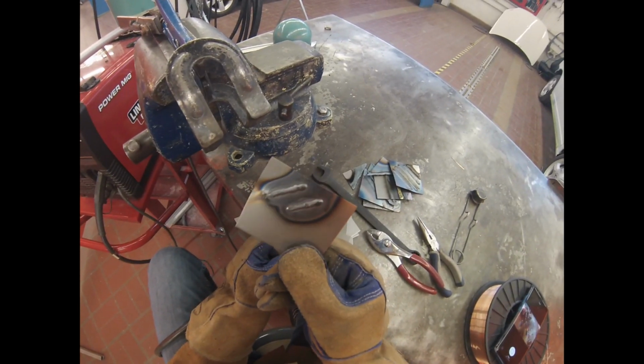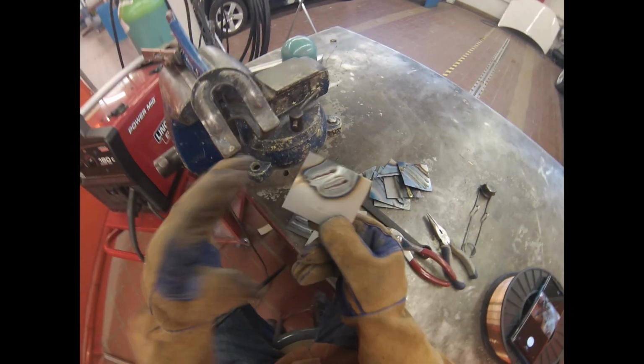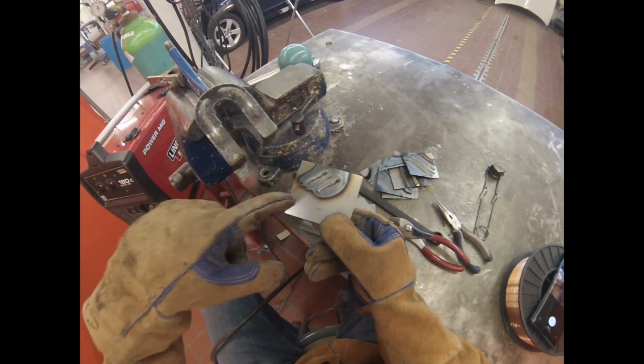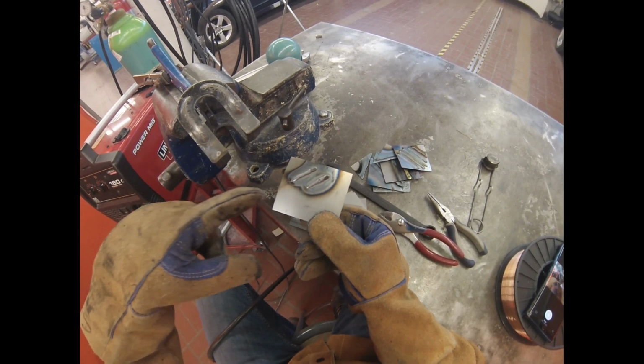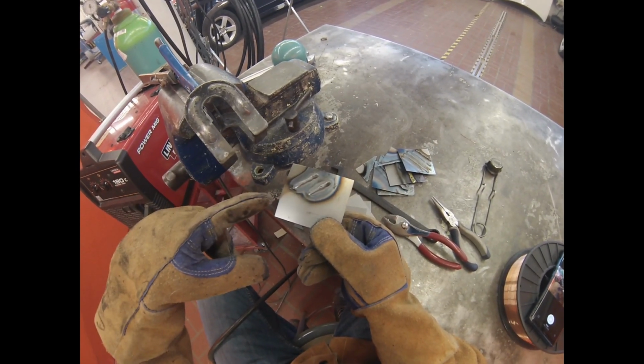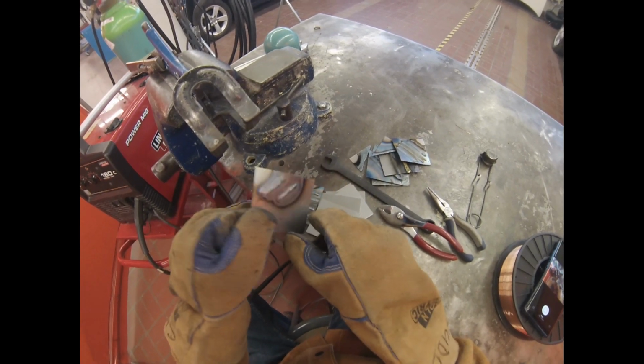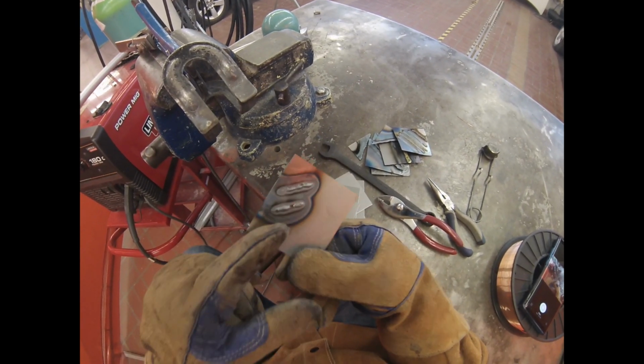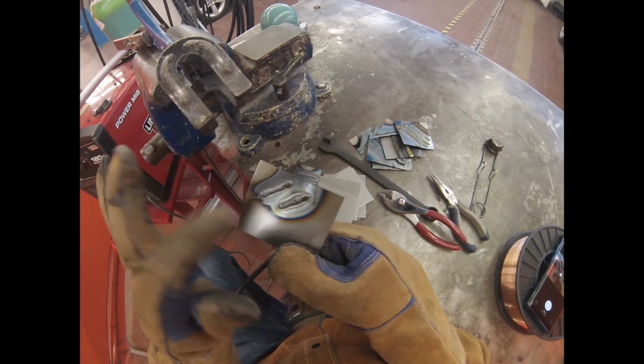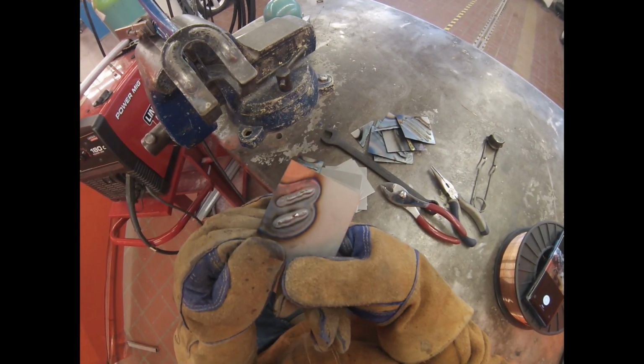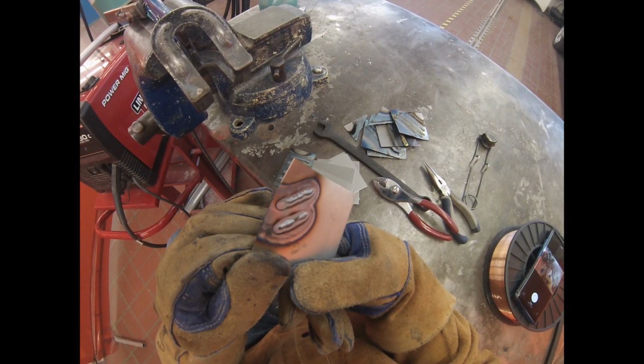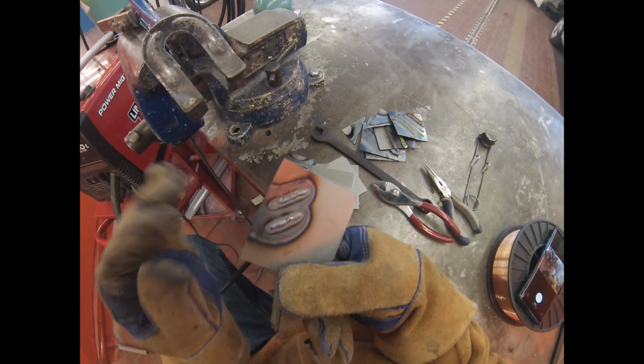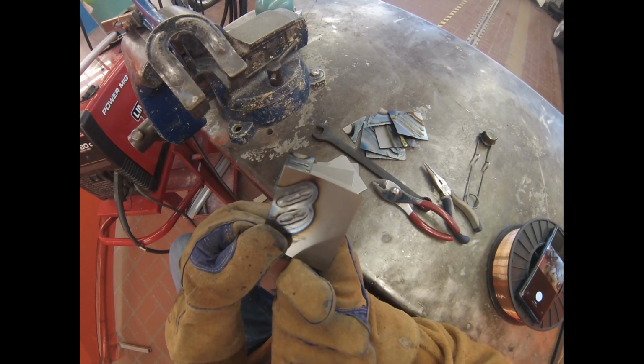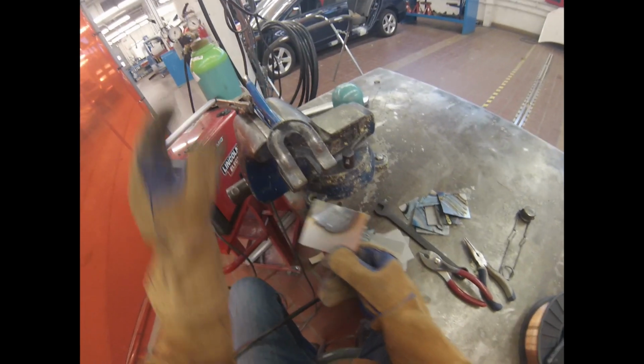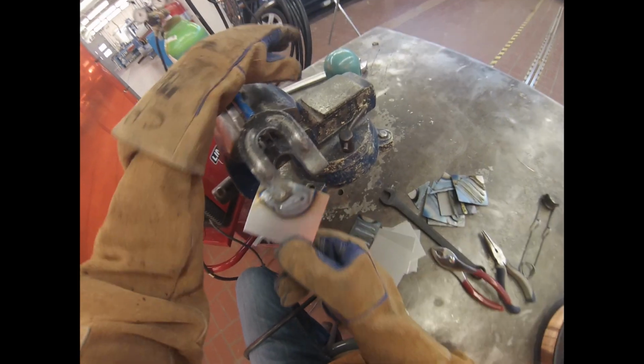Usually what happens when your demo doesn't mess up is with the higher angle, we're not pushing the wire into the metal, so the puddle is moving ahead. So we get a little more wire stick out, and we get a little less force of the heat into the panel. So usually you get less penetration. And then when you point straight down, you get a flatter weld with greater penetration. For some reason, when I did it, they both look exactly, well, you can see this one's a little bit more and that one's a little bit less. But you can just tweak the angle of your torch, and it's just like turning the knobs on the machine, right? So let's try another one again, and maybe there'll actually be a difference this time.